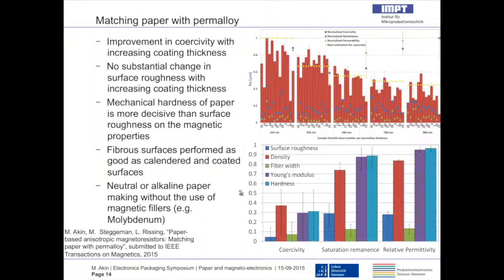Relative permeability, saturation, remanence, and coercivity. And the factors of surface properties and geometrical properties are less decisive on these magnetic properties. So basically, what one might fear, that the surface properties are really challenging for making magnetic coatings work on paper, it's basically the other way. We have to think of the mechanical properties of each of the fibers, that these fibers, once coated, won't warp and induce stresses in the magnetic coating, which worsens the magnetic response of those coatings on paper.